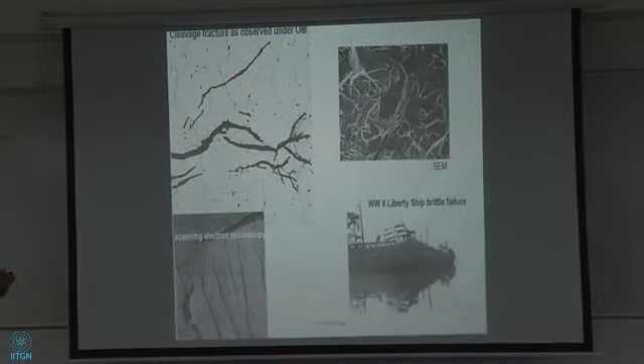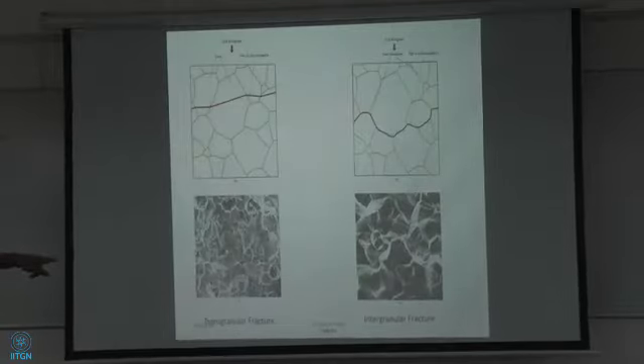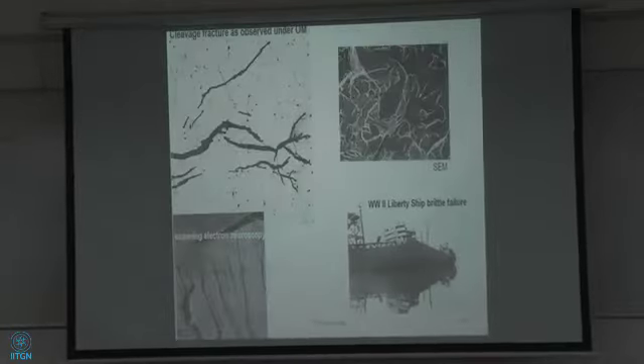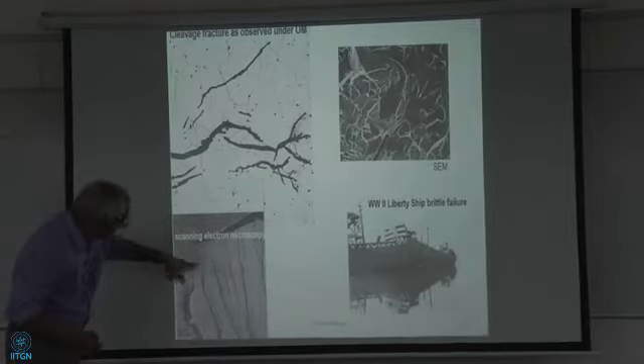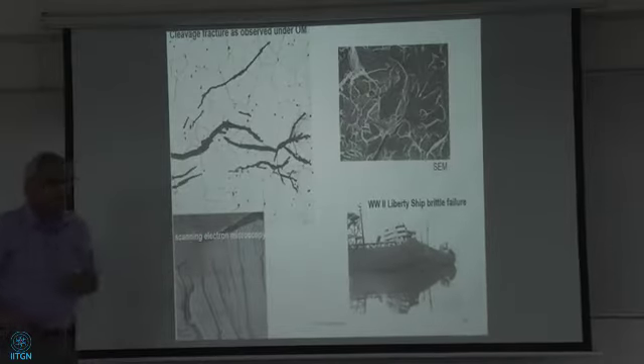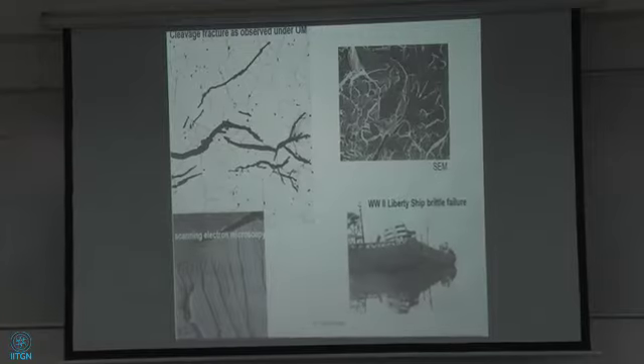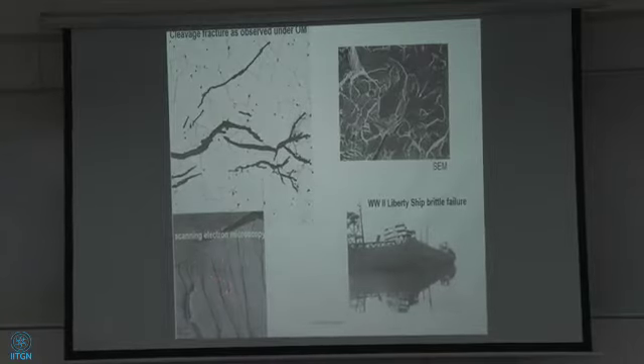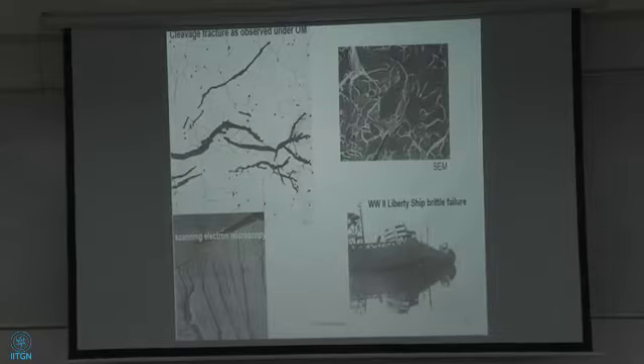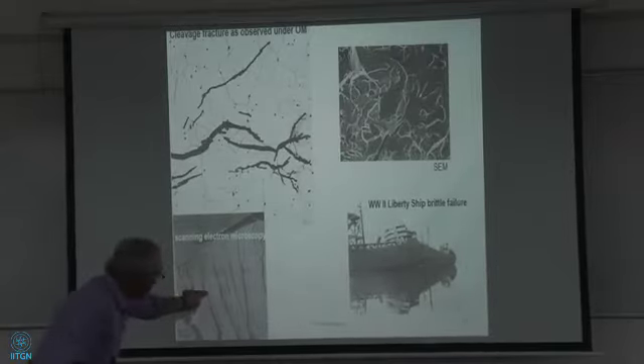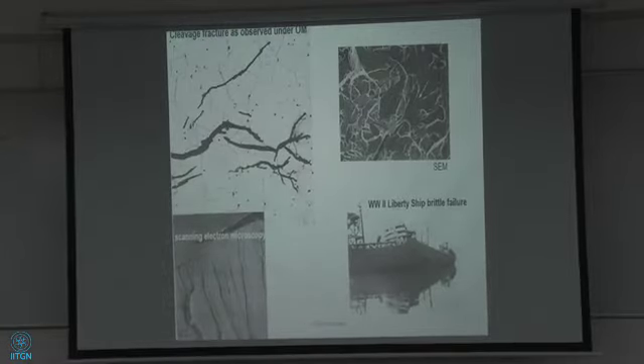And so when you look at the cleavage, this transgranular fracture under optical microscope, this is the way it's going to look like, right? When you look under the scanning electron microscope, of course, it looks like this as well, or you can have very distinct riverline patterns. You see this? These rivers, river tributaries essentially, right? And again, it can look like this. In some materials, it can look like this. But in the case of iron silicon alloys, iron nickel alloys, they all show very good pictures like this. Okay, even titanium will show, beta titanium. I worked on that personally, so I can tell you that's the way they look like. And you can measure the heights of these rivers, and you can put a dislocation theory to the whole thing, which I did with my advisor a long time ago.